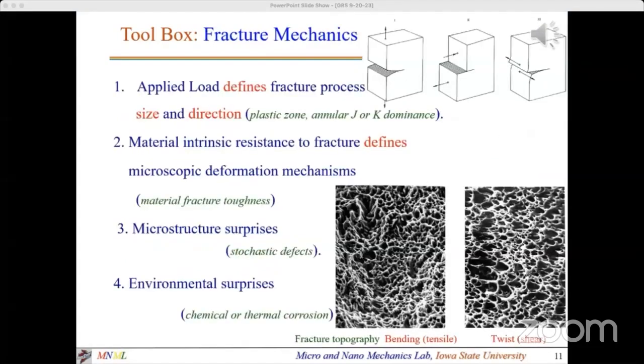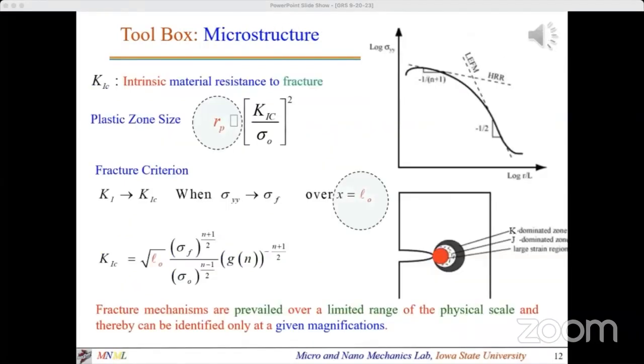In our fracture mechanics toolbox, we have a few things that we know. First, applied load will set a process zone ahead of the crack tip. Second, material resistance to fracture will set the mechanism, which is ductile versus brittle. Third, surprises in the microstructure will provide the weakest link for the crack to propagate. Finally, the process will be affected by environment like temperature or corrosion. In fracture mechanics, we have a parameter called fracture toughness, which is the intrinsic material resistance to fracture. Over a characteristic scale, once the driving forces to fracture reach a critical limit, the local crack propagates. This strength scale, the fracture process zone, is about 2 grains in diameter for brittle materials.